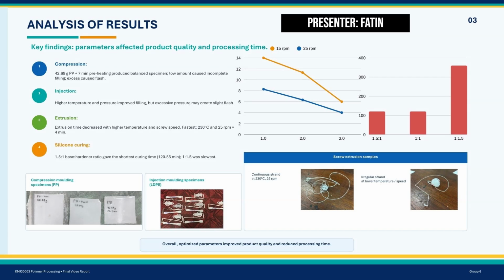For the screw extrusion, the shortest extrusion time of 4 minutes was achieved at 230 degrees Celsius and 25 rpm. This is because the high temperature lowered the melt viscosity of polypropylene, while the higher screw speed improved the material flow through the barrel, reducing the extrusion time.